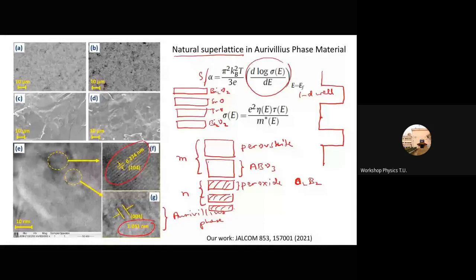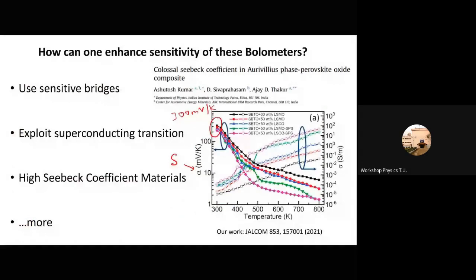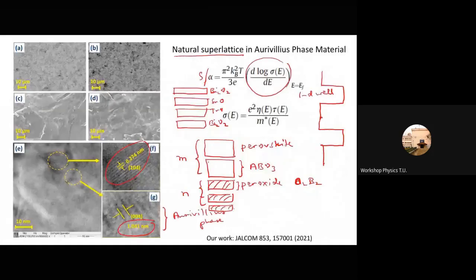In our problem we have not only used the Aurivillius phase, but also added to it an LSMO type of perovskite. It was primarily to make sure that the overall resistance of the sample reduces. So the Aurivillius phase by itself has reasonably high resistivity. So in order to make it much more measurable, we made a composite out of this Aurivillius phase and perovskites, and that led us to extremely high Seebeck coefficients, which was demonstrated to be of utility for our application.